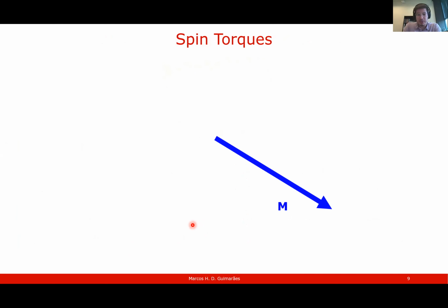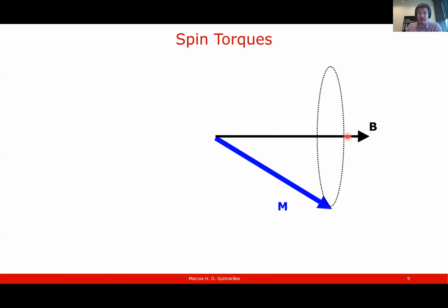But what are spin orbit torques, and what are the symmetries here? So it comes from a very basic ferromagnetic resonance nomenclature, in which we have a magnetic layer with a magnetization pointing in this direction here. And if we apply a magnetic field that is non-collinear with a magnetization, what happens is that this magnetic moment starts to precess around the magnetic field, right? And because the change in magnetic moment with time is a torque, this gives a torque in this direction, which is tangential to the precession orbit over here. So this is called a field torque.